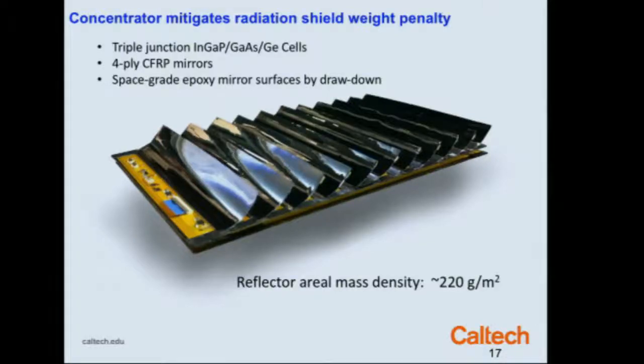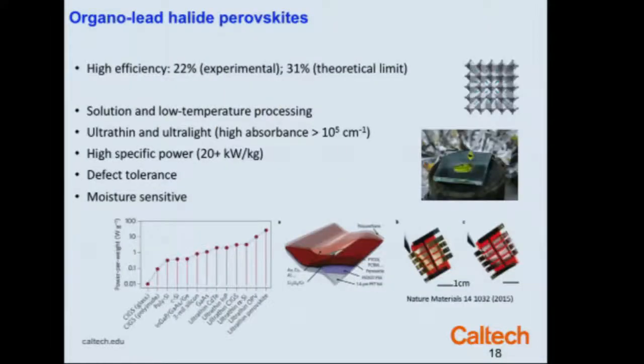These are carbon fiber reinforced structures that are molded, specially laid up and molded, so composites, and upon which we spread a polymer that capillary flow smooths out the surface to make an optical quality mirror. So actually, these are ultralight, high performance components made with space-grade materials, all carbon fiber, and the only metal materials are a few hundred nanometer thick metal thin films.